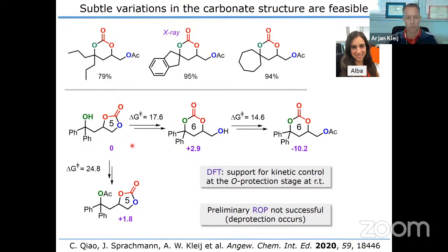We know how it works and what the key driving force is. So if we start with a 5-membered cyclic carbonate, we make the 6-membered one, and then we protect. We see that the second step actually is easier than the first step, and that the intermediate product is thermodynamically uphill. So that also is in line with what we see experimentally. And we do know that the reaction is thermodynamically feasible and kinetically also feasible at room temperature. If we then compare the protection of the 6-membered cyclic carbonate and the 5-membered one, the starting material, then we see that the 5-membered one is much more energy demanding. And this explains nicely why we basically can convert the 5-membered alcohol-free product into the protected 6-membered cyclic carbonate.